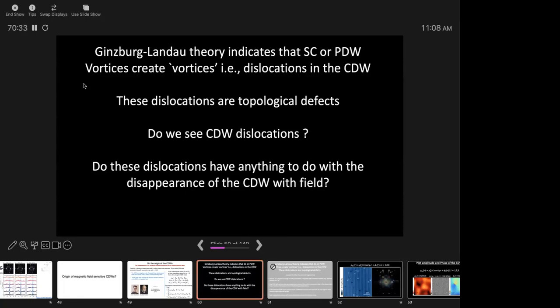So in fact, these vortices should be associated with pairs of dislocations with opposite winding. And in theory, at the center of these dislocations, the amplitude of the charge density wave goes to 0. And therefore, as you increase the magnetic field, you increase the number of vortices and you increase the number of these dislocations with opposite winding. And that's what kills the charge density wave. That's what theory would predict. So let's see if we find these dislocations, okay?